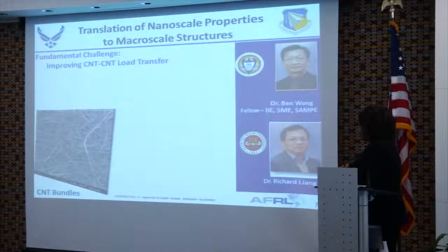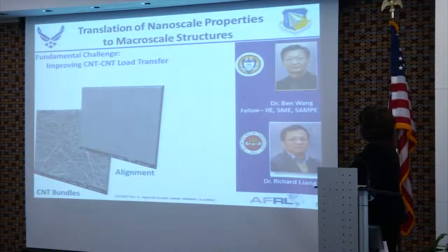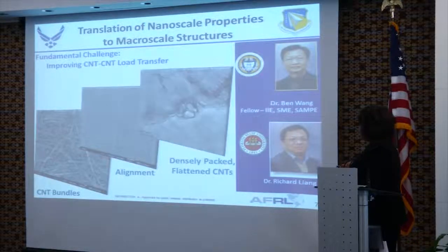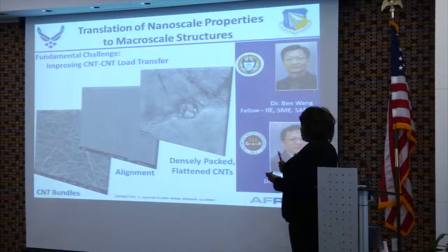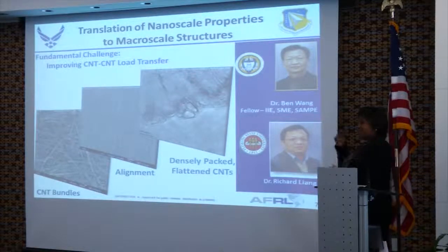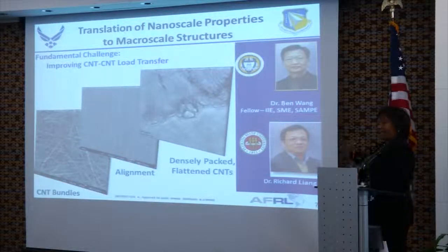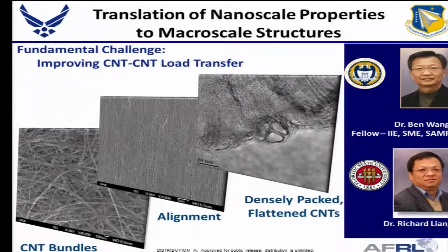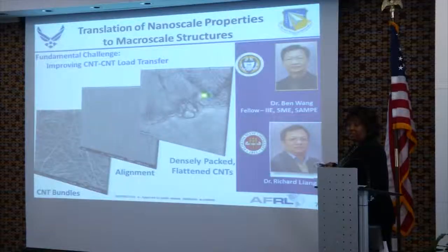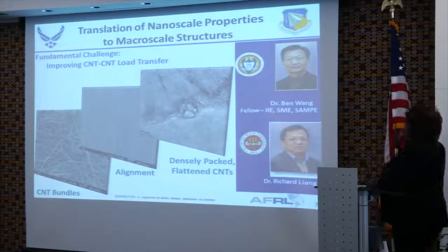And so what they're doing in terms of trying to improve mechanical consolidation is taking something like these CNT bundles that you readily get from many of the processes to make these carbon nanotubes, and looking at how do you get these aligned. These are here in the solid state, kind of brute force alignment of these carbon nanotubes. And then probably even more importantly, how do you get these fully condensed and consolidated such that those tubes start to flatten out and have really close contact with one another, increasing the contact area of the tubes, the stiffness of the tubes, and the friction between these tubes. All that helps to couple the load. And so they're working these aspects of it.